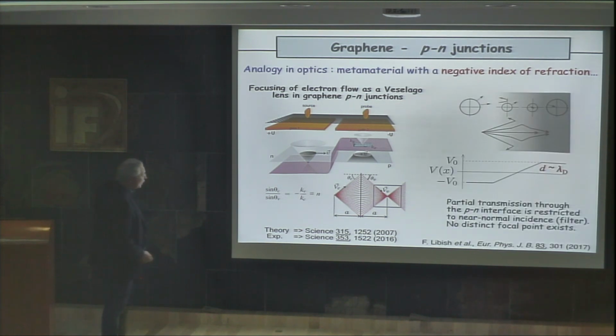Okay, but what we really want to investigate in our case is the fact that sometimes you do not have such an abrupt interface in the p-n junction. This is the case when d is proportional to the de Broglie wavelength. In this case, what happens is that you have a partial transmission through the p-n junction, restricted only to quasi-normal incidence for the trajectory of your electrons. All the other trajectories are bent but are not really transmitted along the system. So there is no focus point as in the previous case.